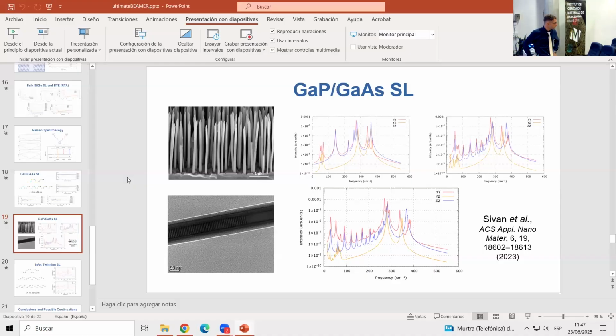So, but why are there peaks that we can only see in the red and blue spectrum, and we cannot see them in the yellow spectrum, for example, and vice versa? The reason is that not every phonon mode, so not any vibrational mode, is optically active. And this has to do with the different response function.